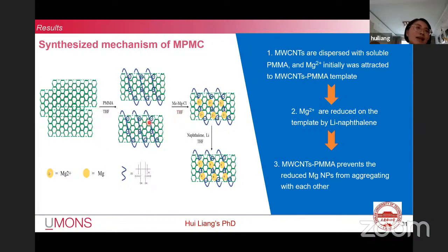The synthesis mechanism of MPMC. First, the carbon nanotubes were dispersed with soluble PMMA, and the Mg ions were initially attracted to the template, and then the Mg ions were reduced on the template by the lithium naphthalenide. Finally, the template prevents the reduced Mg nanoparticles from aggregating with each other.